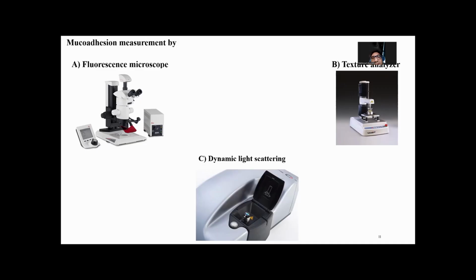Another technique is the texture analyzer. The texture analyzer can measure the force of detachment, or the contact force, between the mucoadhesive polymer and the mucosal membrane. There's another one, dynamic light scattering, using nanoparticles. Here I use this technique to measure the zeta potential, the difference in net charge. Is the net charge decreasing or increasing, starting from the mucosal membrane and the mucoadhesive polymer, whether positive or negative, and after interaction with the mucosal membrane, does the negative charge increase or decrease? This reflects the interaction between the mucoadhesive polymer and the mucosal membrane.